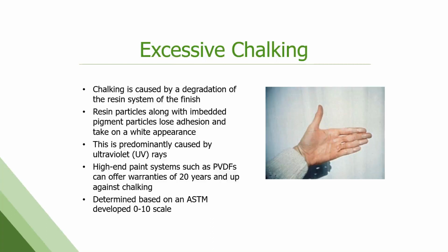This used to be an issue, but I would say in the last 20, 25 years, even the lower end polyesters, the technology and the pigmentation has gotten so good that we rarely see excessive chalking in the field anymore. It just doesn't happen very often. But the high-end warranties are typically 20 years or more for this defect. There is a rating in an ASTM test that dictates what excessive chalking is. The higher the number, the better in this case. So a 10 or a 9 on the scale means that there's really no chalking occurring at all.